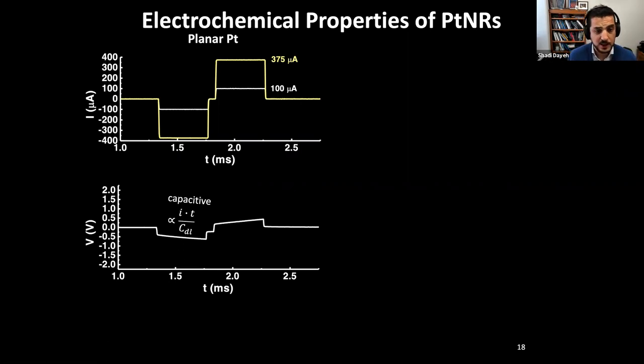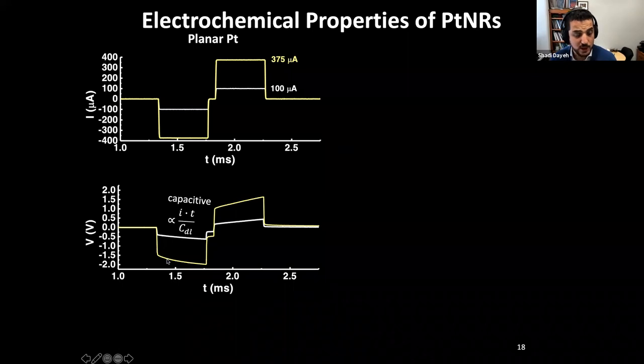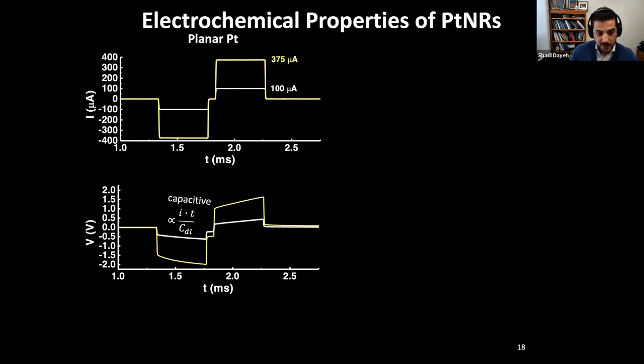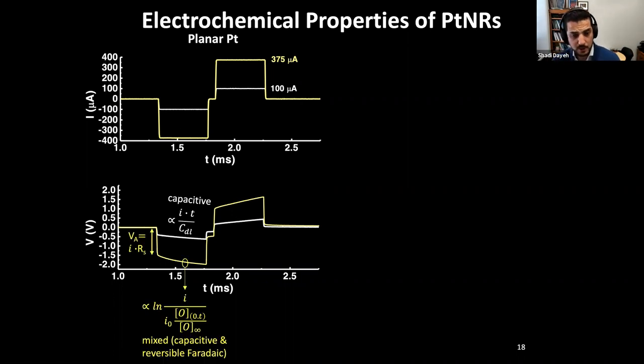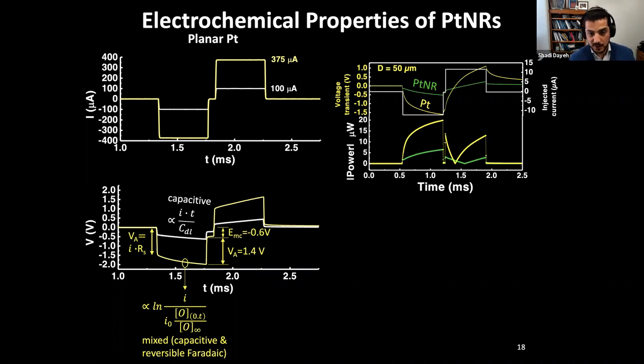So when we inject a current pulse, you would want the potential drop to be as linear as possible, meaning that the charge flows capacitively into the medium. Once we start to have a nonlinear behavior in the measured potential across the electrode, that means we have started initiating Faradaic reactions. And we, of course, want to limit these Faradaic reactions below the water hydrolysis window so that we don't release reactive oxygen into the medium or create hydrogen gas bubbles. And that limit, where we reach the water hydrolysis window, is called the charge injection capacity limit. It takes the value of current that allowed us to see water hydrolysis and divides the amount of charge that we injected by the cross-sectional area of the electrode.